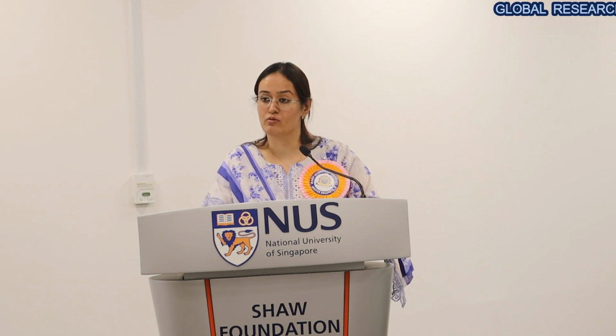Now on the thermal side, this is where we get a lot of excitement in our research. We tested a prototype in the wall where we applied HS36 into the PCM cavities. At an outdoor peak of 37 degrees, the indoor temperature was lowered by 9 degrees centigrade. This was just a start of lowering the temperature. This 9 degree difference, you can achieve more difference if the outside temperature is more than 40.